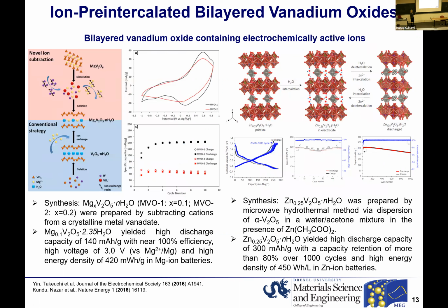And this method has been explored by other groups. For example, Esther Takeuchi used magnesium pre-intercalation to show that they see improved performance in magnesium-ion batteries. My postdoctoral advisor, Professor Linda Nazar, and her group used chemically pre-intercalated zinc in zinc ion cells, and showed that the material demonstrated improved performance as an electrode in zinc ion cells.